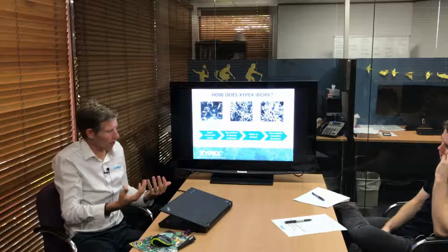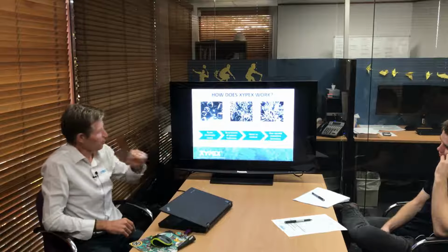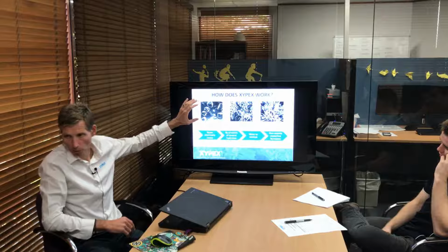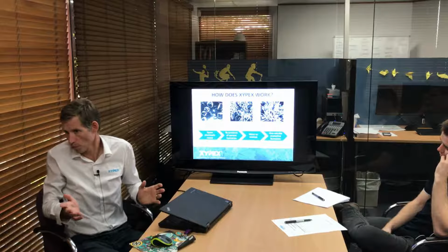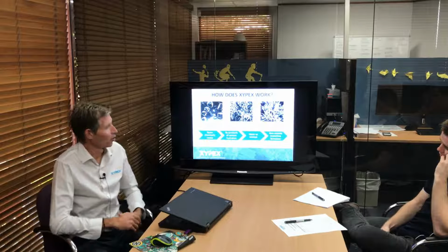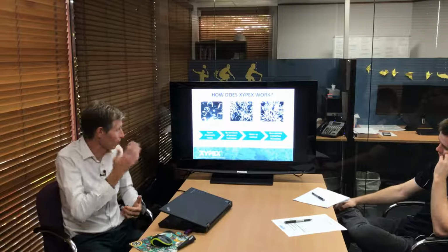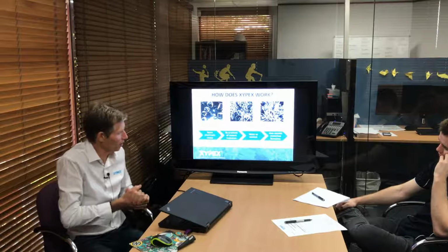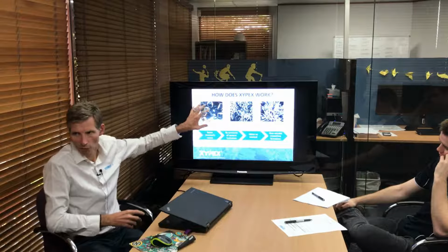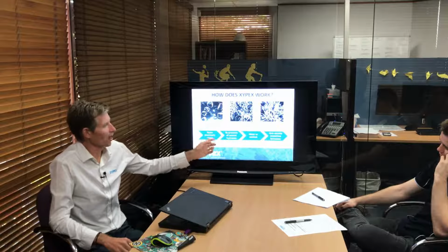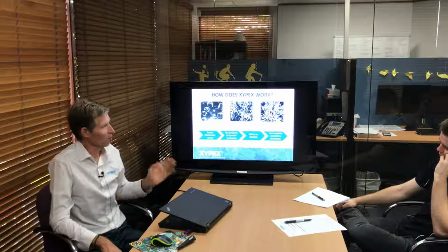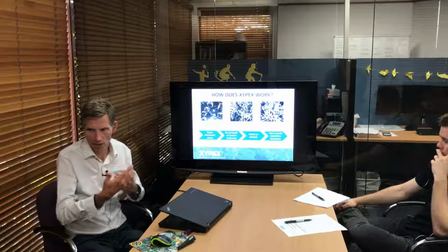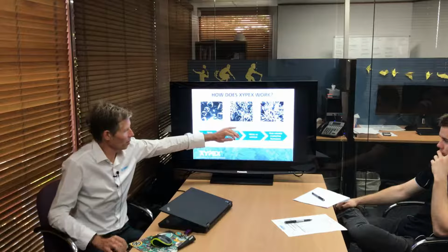So just to show you the differences, what we've got here would be your cubic and rhombic unhydrated particles of the cement hydration process, which normally sit dormant within an untreated concrete element. Now, with the introduction of Xypex crystalline technology, the crystals form within the micropore structure of concrete and essentially within the matrix of the concrete. What happens is we start to fill all these voids and capillary tracts up. That's all by this reaction with the byproducts of the cement hydration process. Now, moisture, or water, is the key component to it. And as you say, when it's going through that hydration process and curing, that's when it starts to take place. So typically speaking, this would be the initiation.